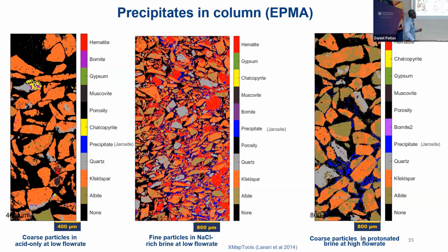Different instances - what I want to tell you here is that if you look at these 3 figures, you can see you could have an instance where your precipitates are going at the entry point of the column rather than all through it. In another case, you could form precipitates along preferential flow pathways all throughout the column. In some instances, you could have it just where the copper sulfides are, not throughout. And whether you form homogeneously throughout the column or heterogeneously, it has different consequences on how much copper you can get, how quick the flow can be, and what's clogging the pore space.